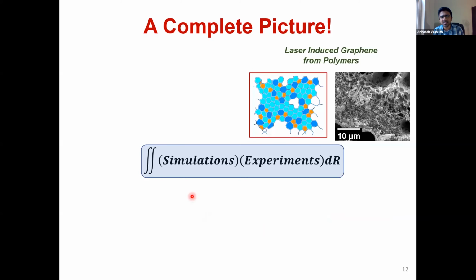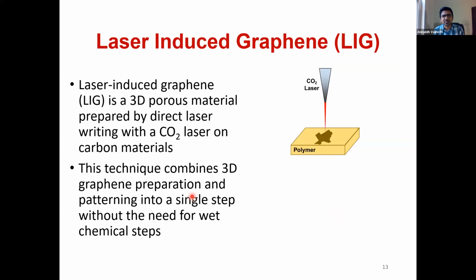It's called laser-induced graphene. It's a single-step process of making a graphitic material. You can say that it's not exactly graphene. It's not planar. It's kind of a foamy structure, so it has some undulations in it. But the main process here is that you take a CO2 laser and you lase a polymer. And by lasing the polymer, you basically change the polymer into an ordered graphitic structure. So it's a very interesting, very cheap, and very straightforward way of making a highly conductive graphitic material.